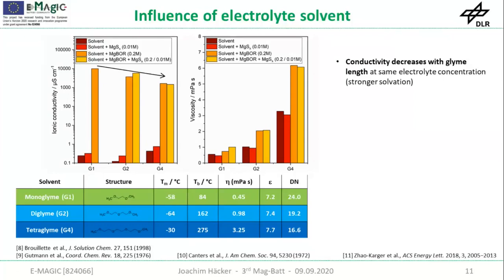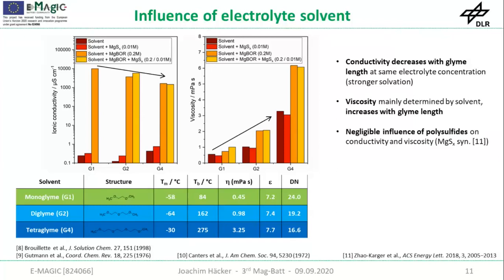and reduces their mobility. So conductivity decreases. In contrast, viscosity increases, which is following the same trend of the pure solvents. So this is mainly determined by the solvent itself. The influence of the polysulfides is negligible, at least in this concentration range. So this is a quite low concentration of 10 millimolar, but higher concentrated polysulfides are not synthesizable yet. But I think it's comparable to practical cells, so I think this might not be an issue to consider at the moment.